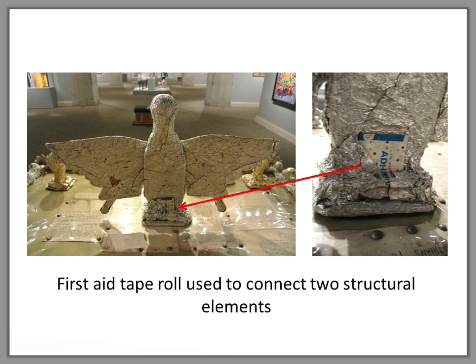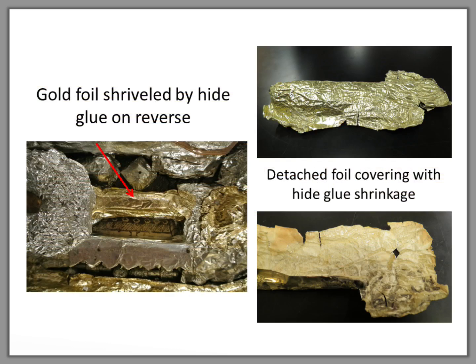The structural material Hampton most relied upon, however, is hide glue, found on 4 detached throne samples and identified by FTIR analysis by comparison with the spectrum of a known sample of degraded hide glue. He may have discovered the utility of this material in discussion with the used furniture purveyors he's known to have frequented in the used furniture district. This material would have been inexpensive and readily available in bulk to be mixed up in individual batches as needed. The strength of this adhesive served Hampton well to some degree, securing layered papers and foils to wooden substrates and to other decorative layers. However, its contractile forces also worked to the artist's disadvantage because glue applied to paper-backed foils caused the shiny surfaces to shrivel and distort, resulting in a withered appearance.